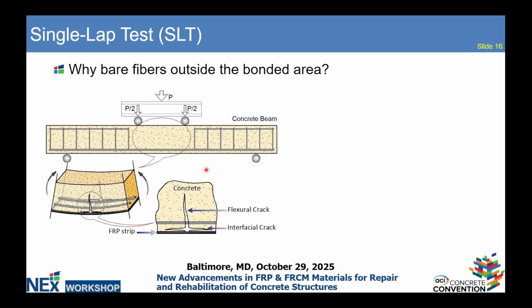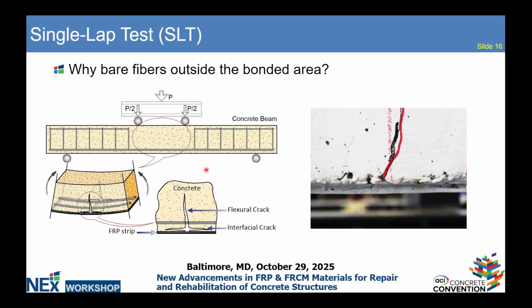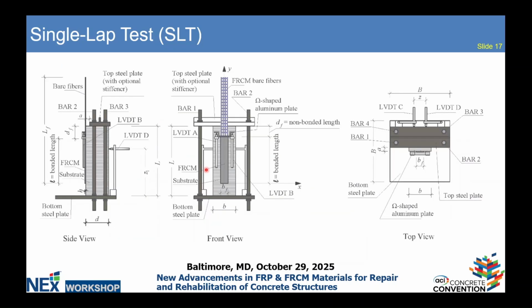You see here at the bottom. In FRCM, because the matrix cracks with the concrete, the crack continues into the matrix. So it's the fibers that are the actual load-carrying item in the cross-sectional analysis, not the FRCM. Here you see some pictures from the ACI 549 documents that we are balloting right now, with all the details.